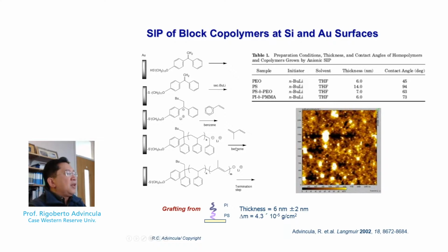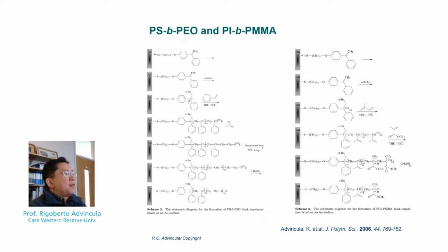Since this is a living anionic polymerization, after depleting all the styrene monomers, we simply add in the isoprene monomer to produce this block of polymers. Not only with isoprene, we were able to achieve this with blocks of polystyrene and polyethylene oxide, and polyisoprene and PMMA. And here are several examples of how we've done it in terms of grafting these copolymers.